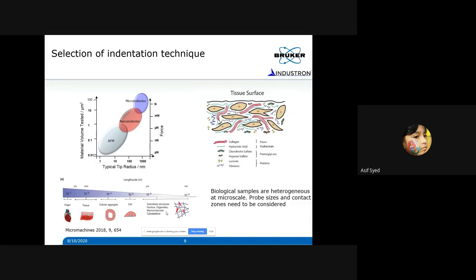So to cover the length scale, you need to have a certain type of instrument. Okay, with a Nanoindenter, actually we can go almost closer to AFM, like 10 nanometers or less than 10 nanometers, and we can go up to 100 microns, hundreds of microns in depth. We can do that with Nanoindenter. Okay, so choosing an instrument also depends upon the length scale that you want to make measurements at. Normally with Nanoindenters, you can pretty much cover most of the length scales that are of interest with respect to biomaterials. But when it comes to DNA, if you want to sense the DNA level forces to split the DNA and things like that, you probably end up using an atomic force microscope for that kind of application.